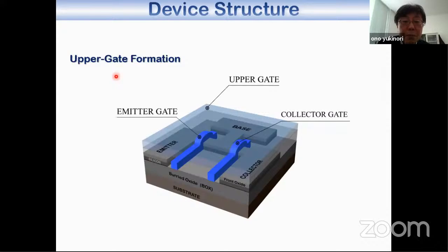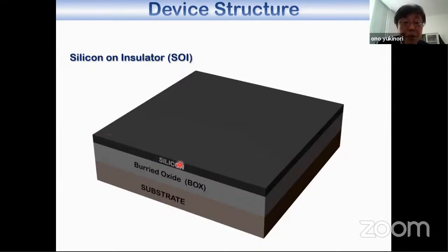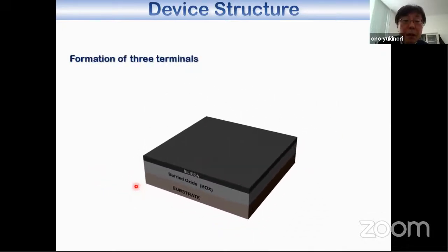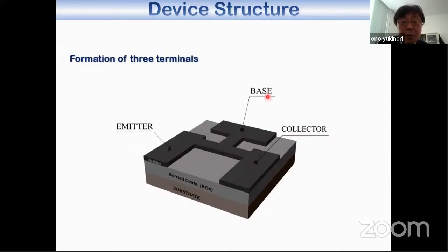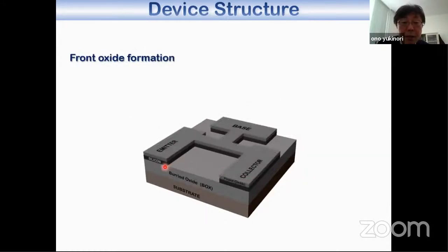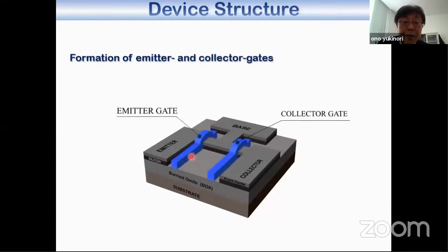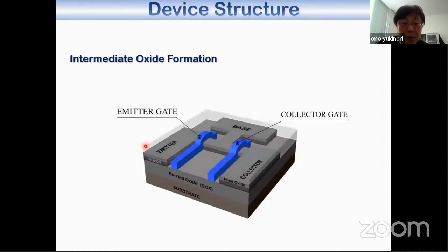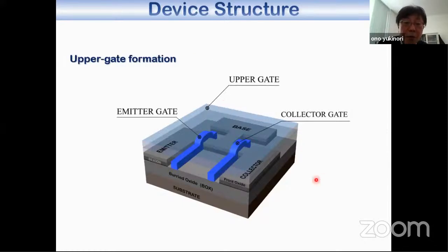Next, I'd like to explain the fabrication process of this device. This is a bird's-eye view. We start with the preparation of the silicon-on-insulator layer, with the top silicon layer thinned down to about 20 nanometers. Then we define the emitter, collector, and the base terminals by using electron lithography. Next, we form the thermal oxide on top. Then we define the fine gates, emitter and collector gates, which are made of polysilicon. Next, we deposit the SiO2, silicon dioxide, film layer. And finally, we define the broad upper gate.